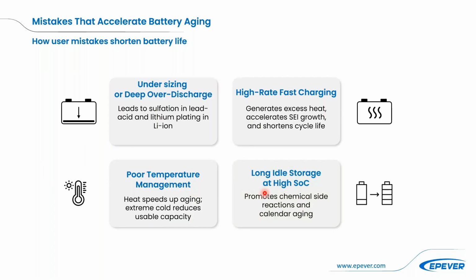And we also have storage issues. Storing batteries fully charged for long periods promotes chemical reactions that lead to calendar aging. So you might have a solar setup that you actually do not use, and your batteries are essentially fully charged, but this is called the idle condition. Chemical reactions are there, and they contribute to aging of the battery. So mild consumption all the time is good. And I have some people in remote locations who have programmed their charge controller just to start a load during the night, a small load that prevents the idle condition for the batteries. So yeah, I'm not sure if that's suitable for all applications, but it is recommended in remote locations where you do not touch the system and the system has no usage for a long period.